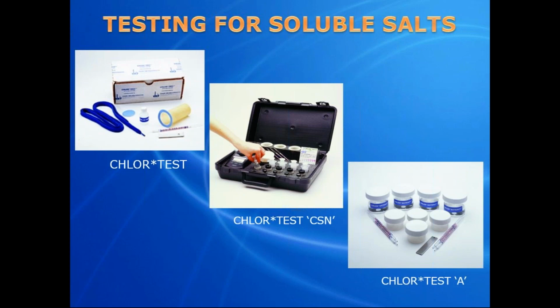It's going to tell you a given surface area in centimeters. And our product is used with the CHLOR*TEST, like I mentioned before, and that CHLOR*TEST is a liquid product, and parts per million is a liquid measurement. So with the sleeve, when we test with the sleeves, the inside area of the circumference of the sleeve is basically right at 10 centimeters square. And the liquid that we use for testing is 10 milliliters of liquid, and therefore the ratio for making the adjustments is 1:1. Therefore, if you see 7 parts per million, it's the equivalent of 7 micrograms per centimeter square. 10 equals 10, etc. So it's very simple. You don't have to do any special math for that.